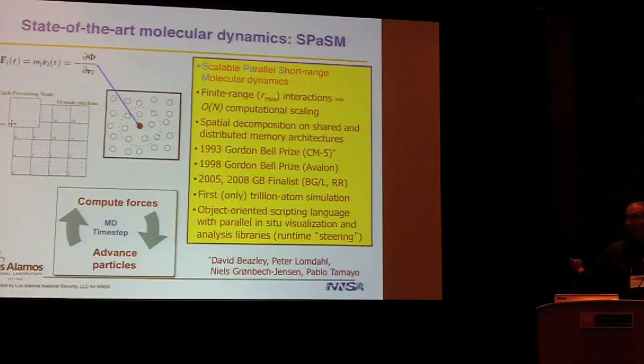So because of this fact, you can implement a straightforward domain decomposition scheme, subdivide your physical system among processors, and then further subdivide that system down to these subdomains of dimensions of the length of this cutoff distance. Then by doing this, the advantage is that for every atom, you don't need to store a list of all of its neighbors and maintain that list. You can just do a rapid search at every time step just by looking at all the other atoms within that subdomain and within the immediately adjacent subdomain. So this gives a straightforward order N implementation.